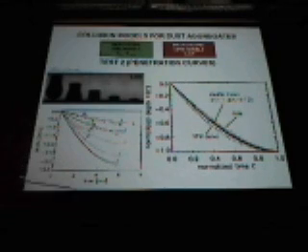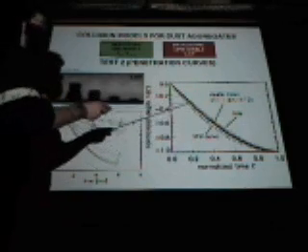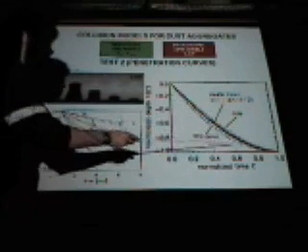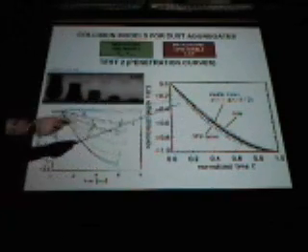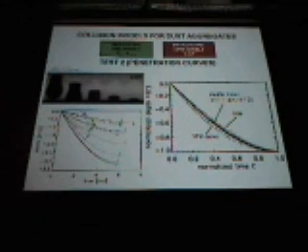So we have depth over time, and we see there are high velocity impacts due to deep penetration and long penetration time, and the slow ones are decelerated very fast. And if you normalize those to the point of first contact and the point of deepest penetration, you get a master curve like that. So all the experiments are plotted here, and this dashed curve is the SPH model of Schäfer, which the guys in Tübingen computed for us.